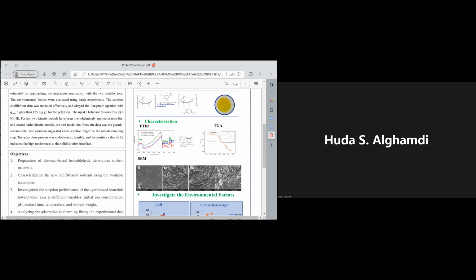What happened in the isotherm studies is that we applied Langmuir, Freundlich, and Temkin. Langmuir displayed a perfect fit for the data with high coefficient values for the two systems, which suggested formation of a monolayer and homogeneous structure. The value QM taken from the Langmuir equation was higher than 125 milligram per gram. And the enhancement in the maximum capacity is owing to the chemical functionalization of the benzaldehyde derivatives. And for the uptake, when we compare between cobalt and nickel, the cobalt was very good in the uptake process. This is for the modeling.